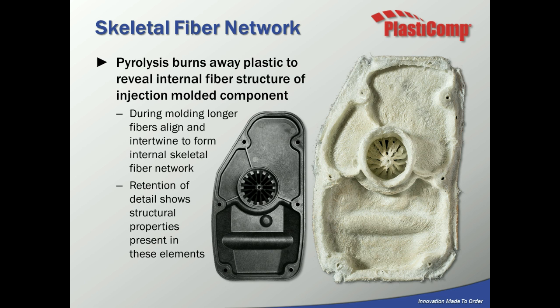It's because now loads can be distributed across wider surface areas of the part. Another couple areas to note in this slide is that if you look in the center, you can see those thin ribs. Well, those thin ribs, as you can see on the white part, are filled with glass. And that's because of that pultrusion process, where we're fully wetting out those fibers, protecting them during the molding process, and allowing them to get into thin sections.